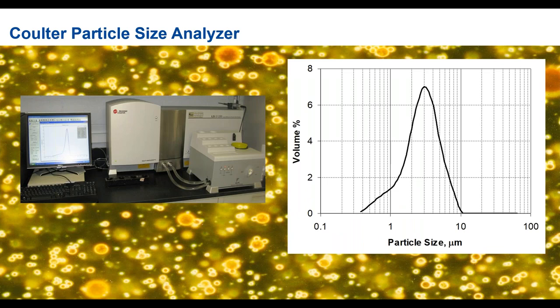From a particle size standpoint, what we want to look at in this product, you'll notice the particle size graph on the screen that came from our laboratory in Charlotte. And what I want you to notice is I told you that latex is a little smaller in particle size. You'll see this little latex bump on the bottom left. Normally, particle size of an emulsion without latex would be a simple normal curve, but that left leg, because of the smaller particle size, you'll see that little latex bump. So if your lab runs particle size, you can sometimes identify the latex in there with that little bump.